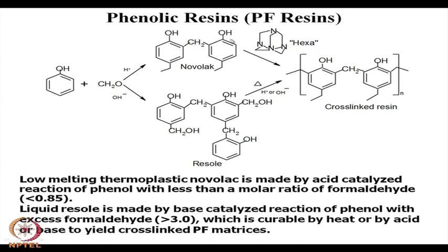Now, this Novolac resin will not cross link itself. To make it cross linkable, another cross linking agent known as hexamethylene tetramine, its formula is a little complicated here. Hexamethylene tetramine, known as hexa technically, decomposes to form amine and formaldehyde. This amine and formaldehyde basically becomes the reactive cross linking agent with this Novolac resin to form a three dimensional